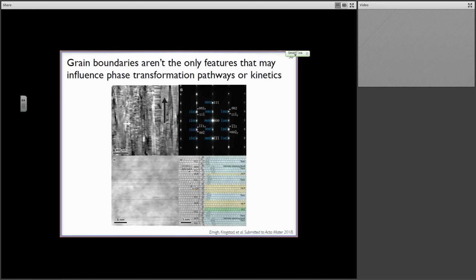So we're going to think about this. Like I said, we have these grain boundaries which are accelerating diffusion. We have some other defects in these microstructures as well, and we need to pay attention to those as well. There are these grain boundaries, there are high density of vacancies, but there are also these planar faults. And so you can see those here. In this particular micrograph, the black arrow indicates the direction of growth of this microstructure. And the white arrows are just trying to point to some of these planar defects that we think are interesting.